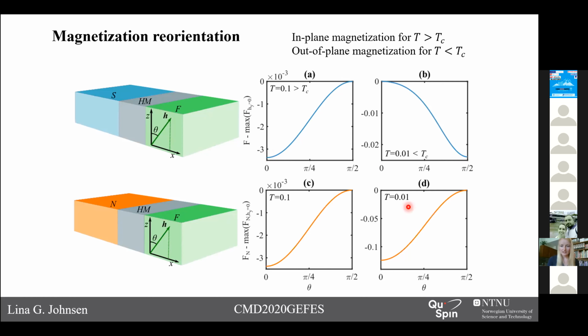In panels C and D, we have plotted the exact same free energy curves for the same temperatures, but with a system where we instead have a normal metal and no superconducting phase transition. Then we see that there is no shift in the minimum of the free energy, so this reorientation must be caused by the superconducting phase transition. In this model, we have not yet taken into account the shape anisotropy of the ferromagnet, so for this to happen, we would expect that we need a thin ferromagnetic layer with as weak shape anisotropy as possible.